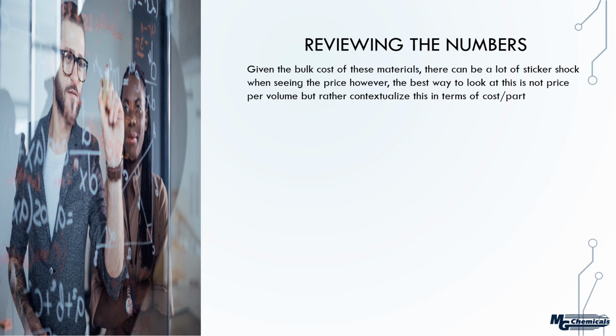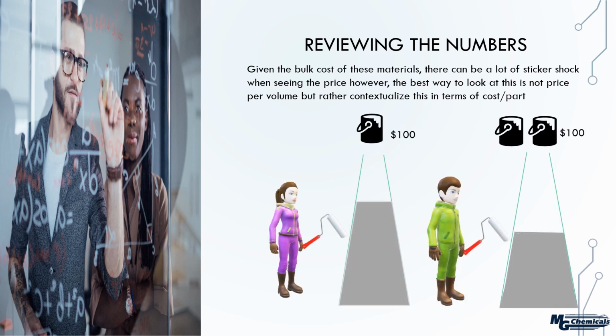So when we look at the numbers associated with costing for these materials, we have to contextualize it more in terms of the cost per part rather than cost per volume. So to do that, let's consider the examples here. The woman on the left has chosen a more premium paint valued at about $100 a gallon. But then you can judge the efficiency of this paint based on how much of the flooring she was able to coat. The young man on the right purchased cheaper products at $50 per gallon, and having bought the same amount, still was not able to coat the same surface area.